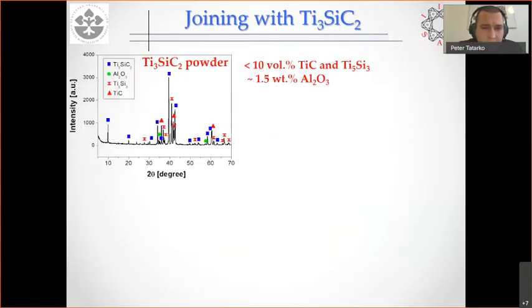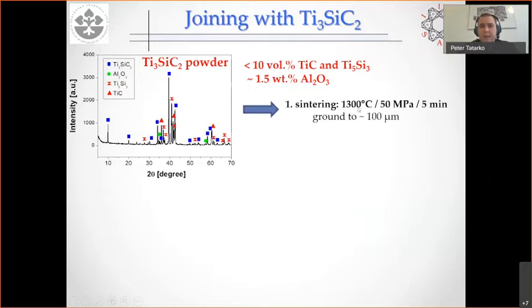Very briefly, we synthesized this MAX phase powder using microwave sintering, and you can see there are very typical impurities for these materials: titanium carbide and titanium silicides. We intentionally added some alumina because alumina helps the sintering of this material and also helps oxidation protection of the material. So this powder was sintered by SPS at 1300.